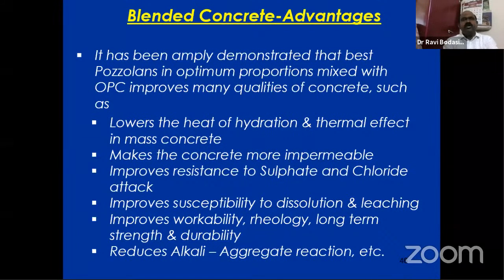It has been demonstrated that the best pozzolanic material in optimum proportion mixed with OPC improves many qualities of concrete, such as lowering the heat of hydration. Once the heat of hydration is lowered, your plastic shrinkage cracks will come down drastically. If the plastic shrinkage cracks are not there, there is no chance of water, moisture or air penetrating through the cracks. It is also good for the thermal effect in mass concretes, makes the concrete more impermeable, improves resistance to sulphate and chloride attacks, improves the dilution and leaching effect and workability, enhances long-term strength and durability, and also reduces the alkali aggregate reaction.